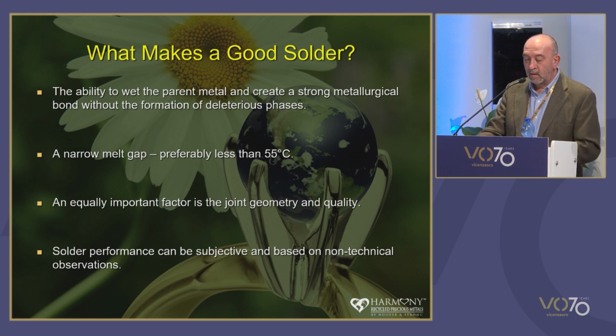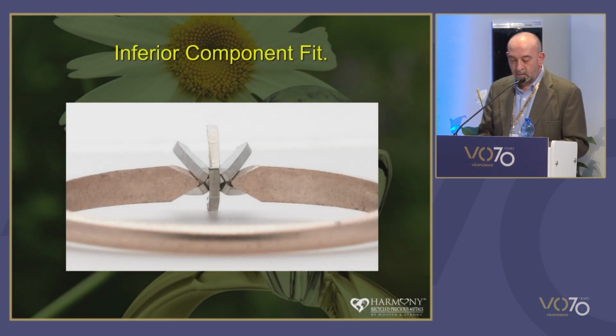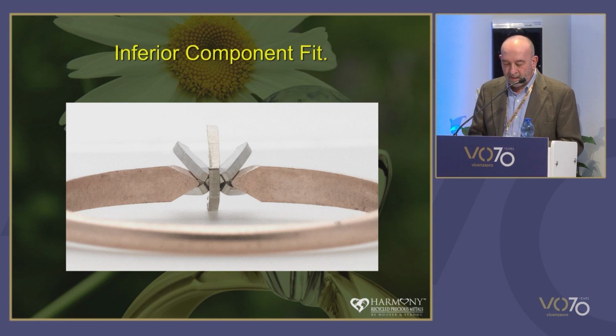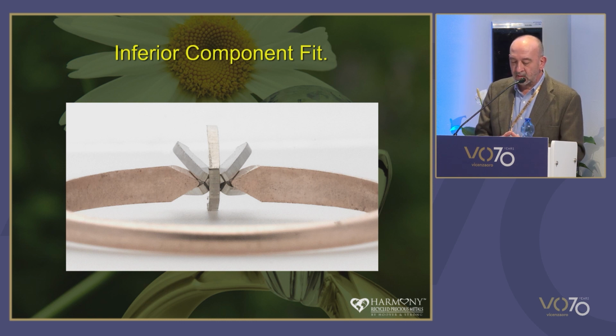So the original problem we had at the company that I work for, Hoover & Strong, we did a full investigation and we determined that the problem was not with the solder. All the criteria for the solders worked and they all fitted and they were all excellent. When furnace soldered, then something changed. And the problem was with the quality of the joints.